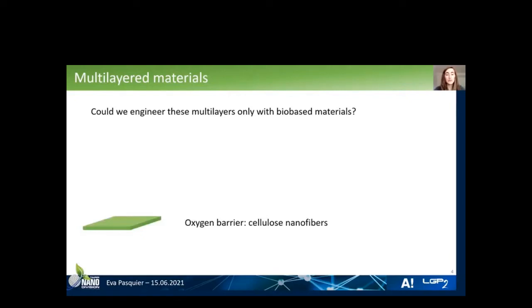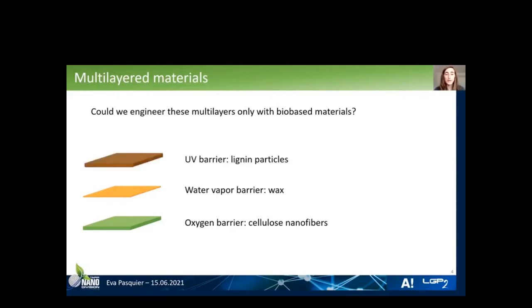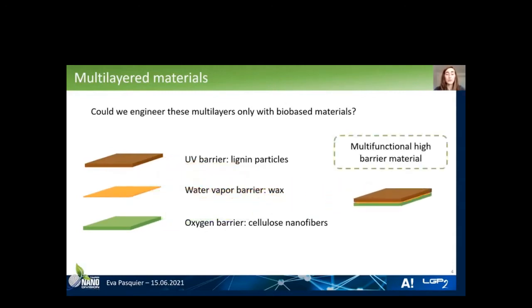And the first component is cellulose nanofibers. It's known to have good oxygen barrier properties. Then we added some wax because it can form a continuous and non-porous layer that will have really good water vapor barrier properties. And then we wanted to have some lignin particles because they can increase the UV blocking property while keeping some transparency. And it is also an antioxidant material. So this would form a multifunctional and high barrier material.